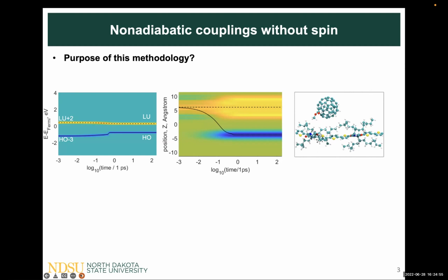In this previous project, the interface, or the charge transfer, was explored in the Z direction. The bottom chemical structure is the DPP polymer, and the top one is the PCBM acceptor unit. To quantify the charge transfer, last week we measured the difference, in the middle figure, between the positive and negative charge, defined it as a dipole, and the derivative of that dipole gave us the current density.